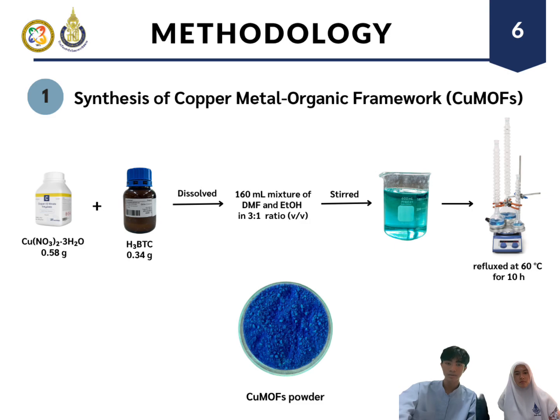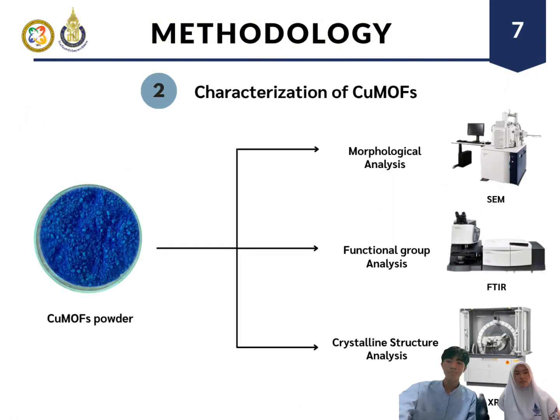For the first methodology, copper MOF was synthesized using copper nitrate and H3BTC in DMF and ethanol in a 3:1 ratio. The mixture was stirred and refluxed at 60 degrees Celsius for 10 hours to obtain blue copper MOF powder. Next, the copper MOF powder was characterized to study its properties using SEM, FTIR, and XRD.